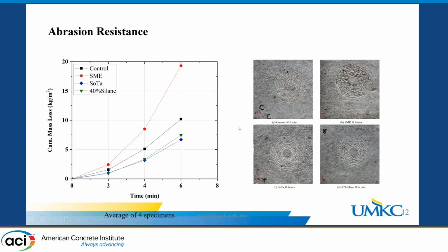You may ask what the correlation is between abrasion resistance of concrete and corrosion mitigation. The answer comes from correlating this abrasion data with the depth of sealer penetration, because research has shown that concrete pavement wears 0.17 millimeter each year. So over time, if we have a bad concrete, the surface will wear, and at the same time we cannot trace the sealer material.